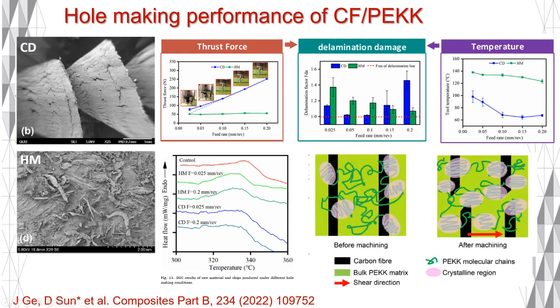One exciting new finding we made here is the discovery that machining-induced shear force and high temperature have led to a significant increase in the PEKK matrix crystallinity at the machining interface. And this may subsequently enhance the material stiffness, strength, and fracture toughness around the machined surface.